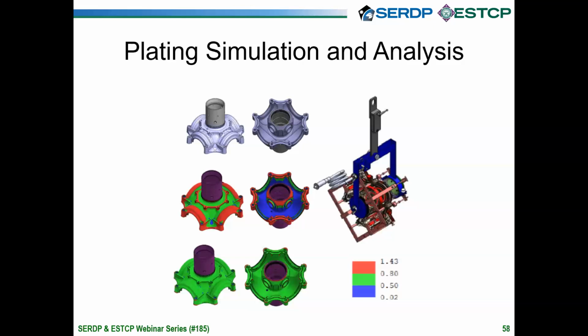This just shows how conforming anodes are designed. So at the top, you'll see just a 3D solid model of the C-130 propeller barrel hub. The gray area, both on the left there, that barrel itself, and then the inside of the barrel is not zinc-nickel coated. So that would be masked during the plating process. It's HVOF or hard chrome plated. And that's what you also see in purple in the next two images, things that are masked and things that are not plated.